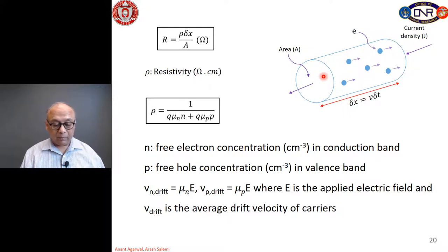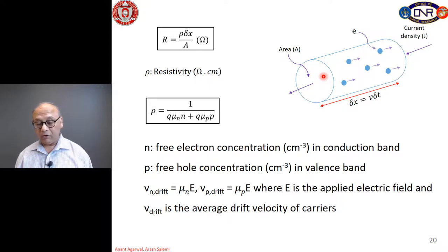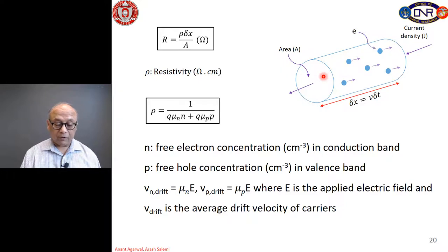That drift velocity is described at the bottom here. You can see that the drift velocity is proportional to the electric field. Obviously, if we apply a higher electric field, the velocity of the electrons will increase, again, we are talking only about the average drift velocity. The proportionality constant is called the electron mobility in this case, mu n, and for holes it is called mu p, which is the hole mobility. Now, the resistance of this material is simply the resistivity times the length divided by the area, and resistivity is given by the number of electrons, number of holes, and their respective mobilities by the given expression.